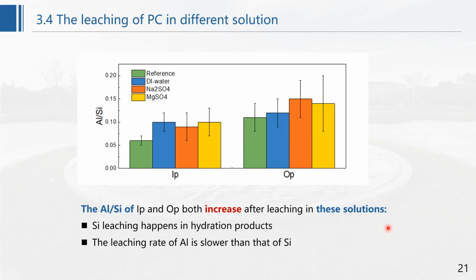Here is the change of aluminum to silica ratio of hydration products after leaching. After leaching, the aluminum to silica ratio of inner product and outer product both increase, which indicates that the leaching rate of aluminum is slower than that of silica.